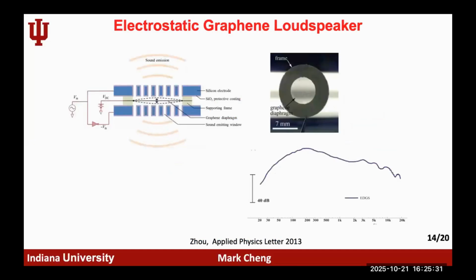And if you can use a different material, right? A couple of years ago, there was the question of whether we can use graphene. Because graphene turned out to be a really thin material, and it's very mechanically robust. So how about you drop in graphene? Okay, but graphene is not a piezoelectric material. But you can use it as a flat electrode. So in this paper, they are just using the electrostatic force. They are driving at pretty high voltage, because usually electrostatic actuation for the micro scale, you have to go to almost 30 volts to 100 volts. So that's still kind of a challenge here.